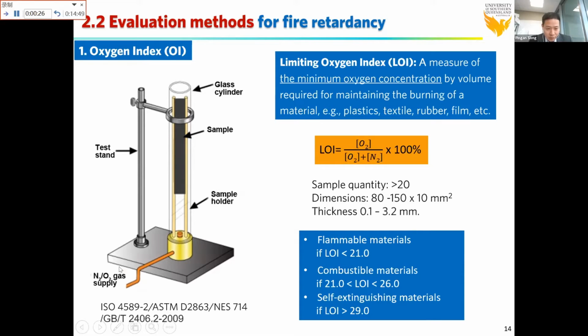Here we have an oxygen and nitrogen mixed gas supply. This is the sample holder; we mount the sample on the holder, and this is a glass cylinder. You ignite the sample from the top while adjusting the oxygen content until you can ignite the sample. At that stage, the oxygen concentration is the LOI of the polymer.